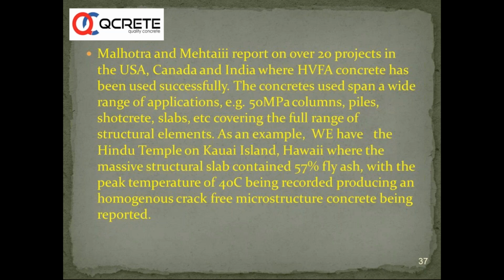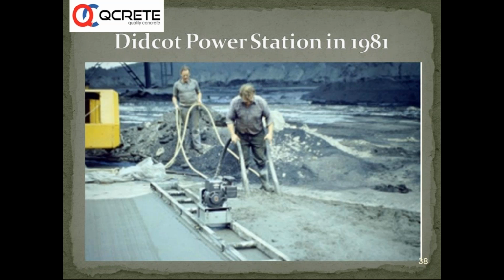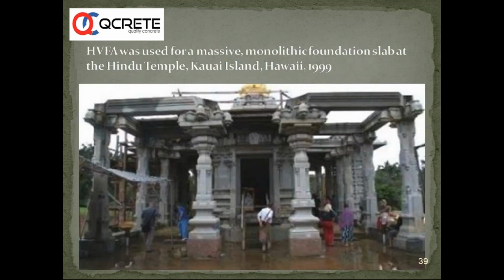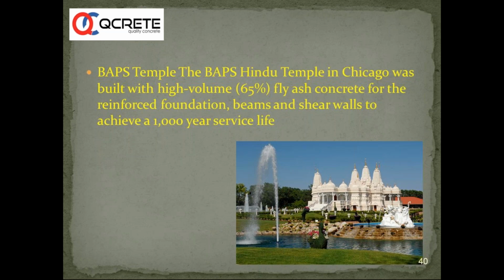We have examples. We have the Hindu temple in Kauai Island, Hawaii, where massive structural slab, 57% fly ash has been done, with the peak temperature of 40 degrees being recorded, producing homogeneous crack-free microstructure concrete being reported. So we can see Didcot Power Station in 1981 when they used high volume fly ash concrete, and this temple with about 57% fly ash. And another Hindu temple in Chicago, built with high volume fly ash, 65% fly ash concrete for reinforced foundation beams and shear walls to achieve 1,000-year service life. So somebody is thinking of 1,000-year service life, and somebody has incorporated 65% fly ash. In these structures, they have specified long-term strengths. So it is not new, actually. High volume fly ash concrete has been tried and it's successfully used, actually.